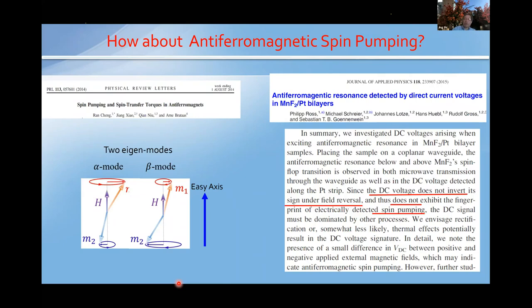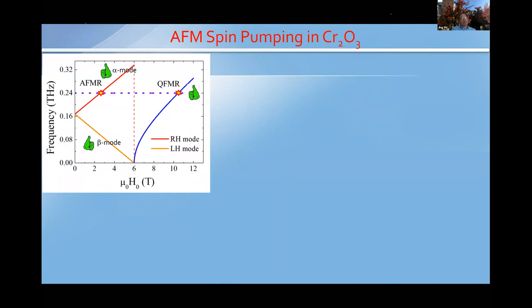So the first experiment we proposed to do was in late 2016 on nickel oxide. We went to the free electron source in Dresden and tried to excite the antiferromagnet. We started with the two magnon absorption process we observed in Raman, and tried to look for a similar signature around that transition condition. We didn't succeed. Then we came back and analyzed our data, and realized that the frequency is not really correct. So we looked for other materials. We found chromia has the right frequency that can be accessed by a capability located in our backyard, UC Santa Barbara.